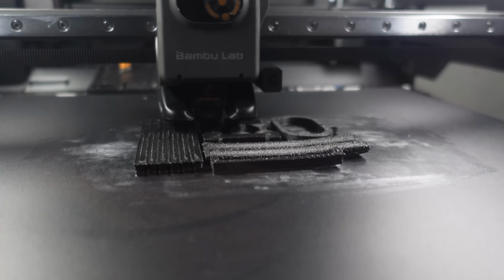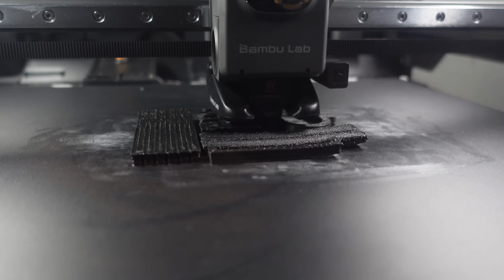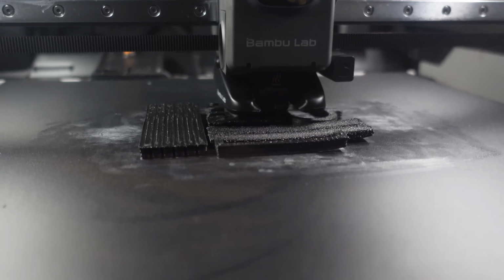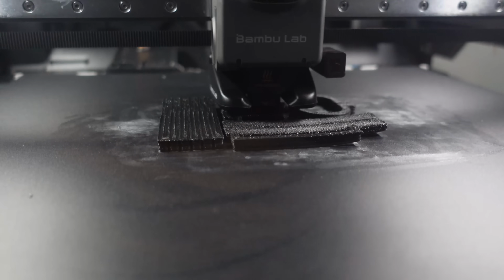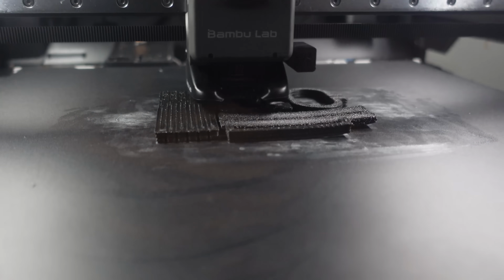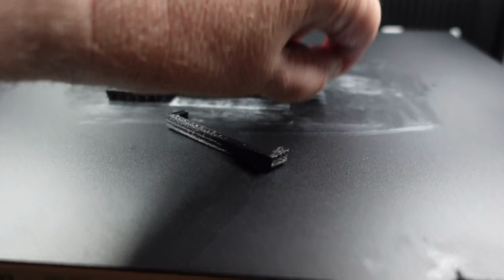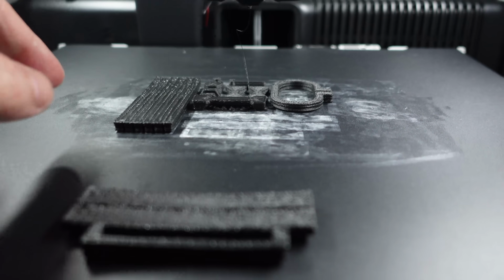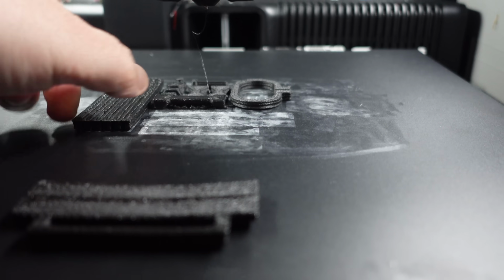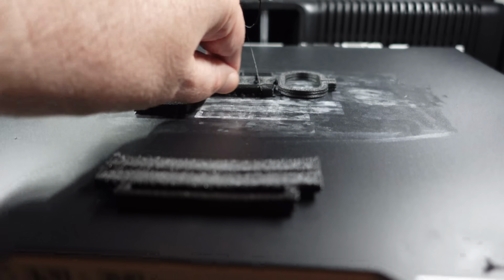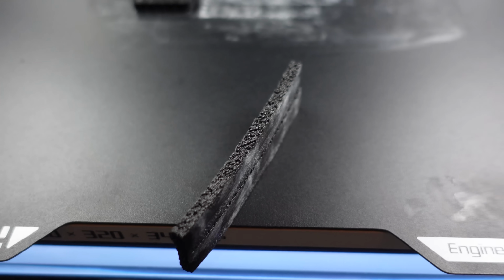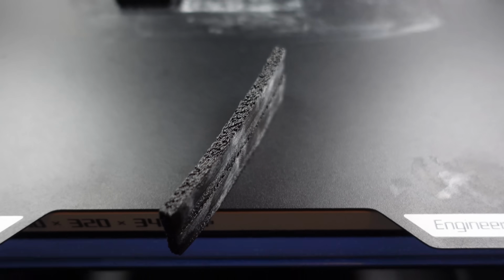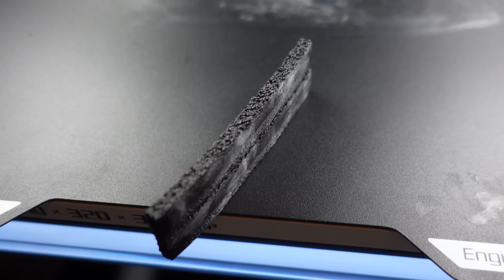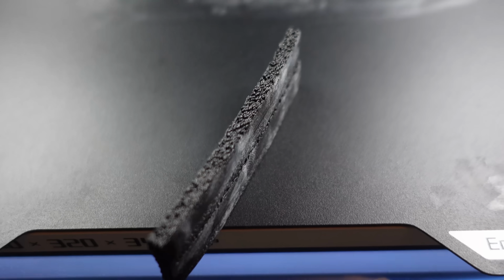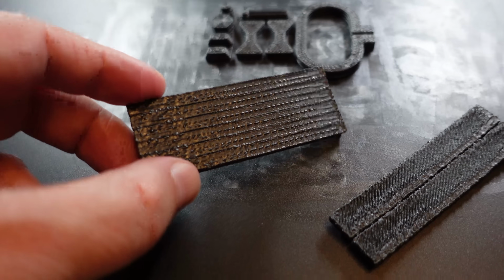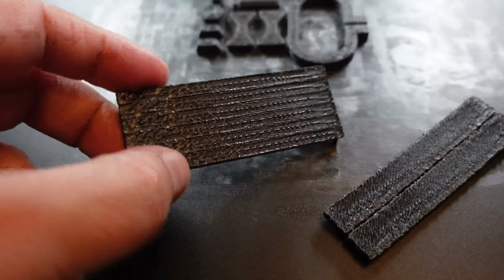With the first attempt I have to stop the printing, warping, and looks like not a dried filament, but this was quite long drying, 85 degrees Celsius, 12 hours. Adhesion is acceptable, so this means the warping is the problem. And look at these side surfaces, looks like a huge over extrusion, but the reason for this is that the filament is not fully dried. And that over extrusion is so big that these test objects fuse together.